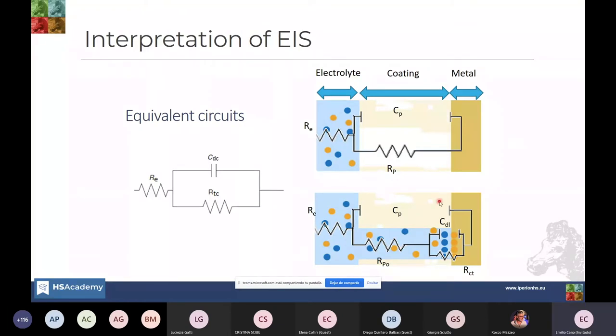When this coating is damaged, we have a slightly more complex equivalent circuit, in which we have again the resistance of the pores and the capacitance of the polymer or the coating, but inside, at the bottom of this pore, we have in series another capacitance and resistance, which correspond again to the double layer and the charge transfer resistance. In this case, this part is equivalent to this part in the circuit on the left.